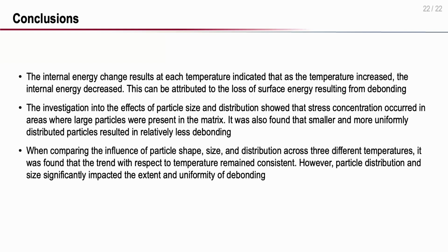Finally, we have 3 main conclusions. First one is that the internal energy change results at each temperature indicated that as temperature increased, the internal energy decreased. Second one is that the investigation into the effect of particle size and distribution showed that stress concentration occurred in areas where large particles were present in the matrix. It was also found that smaller and more uniformly distributed particles result in relatively less debonding. And last but not least, when comparing the influence of particle shape, size, and distribution across 3 different temperatures, it was found that the trend with respect to temperature remained consistent, but particle distribution and size significantly impacted the extent and uniformity of debonding.